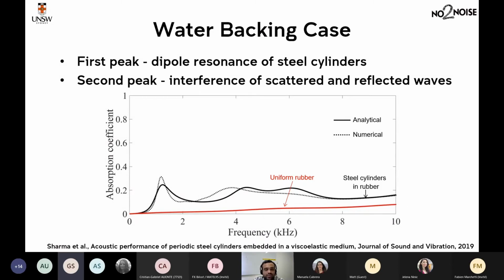one of the advantages of using hard inclusions is that the performance here does not change with hydrostatic pressure. I mean, it's not significantly affected when you apply hydrostatic pressure. Whereas when you have voided inclusions, the performance may significantly degrade when you apply hydrostatic pressure. So that's one of the advantages of using hard inclusions. You see there are mainly two peaks, one peak over here and one peak over here.